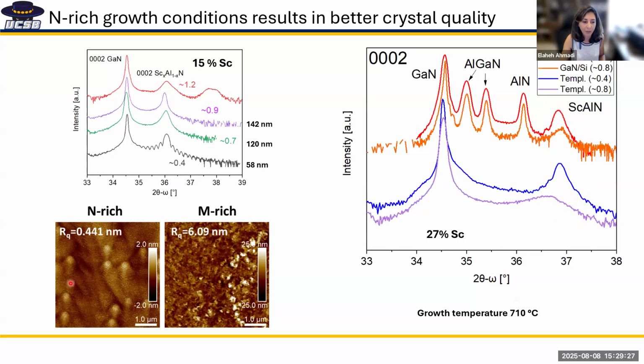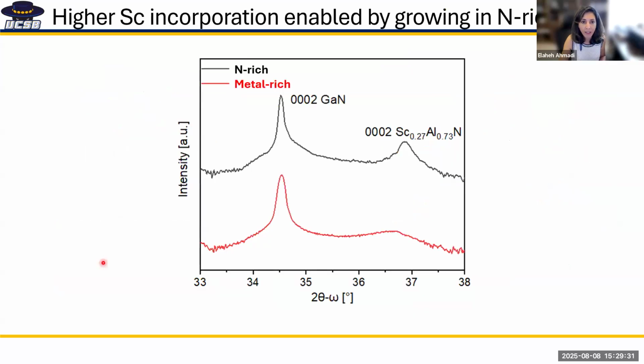And as I mentioned earlier, the AFM also looks better. This actually allows us, if we go to nitrogen rich, to push the scandium incorporation higher. For instance, when we grow metal rich, we see that for 27% scandium, we hardly get a peak, and that shows that the crystal quality is very poor. But when we go to nitrogen rich, we can get a very high quality peak from the X-ray.